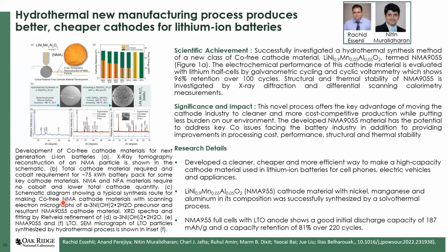So one of the core strengths of our group is doing synthesis. And Rashid is an expert in synthesizing materials and scaling up materials after making them. So you can make materials of the order of, I don't know, 50 grams or so to do the initial test. And if the material shows good performance, then you have to scale it up to maybe kilogram level, and then use that along with the battery manufacturing facility to do a lot of testing to see how good this material is. And Rashid is an expert in it.